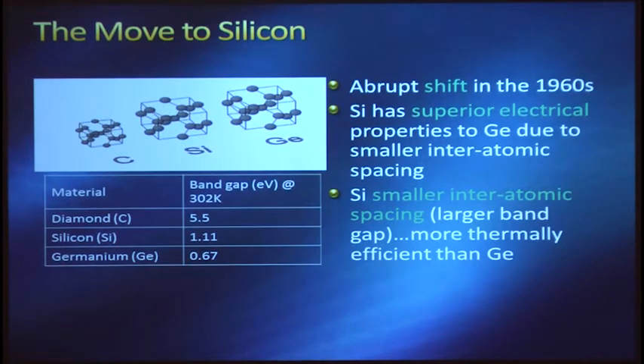And that allows it to be a much larger gap as compared to germanium, right? So it had to take much more thermal energy to be able to switch the electrons out of the ground state and into the vacuum ambient. So we can see that the silicon gap size is almost twice that of germanium. And if we look to diamond, we see it's nearly 5 times that.